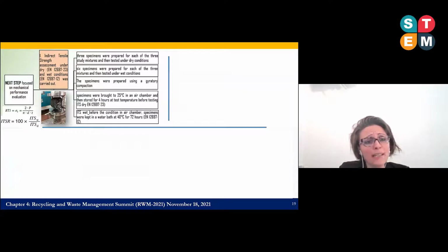The next step focused on mechanical performance evaluation of these mixtures. In particular, we identified the indirect tensile strength. That is the common static test that we carry out on asphalt mixtures, called hot asphalt mixtures, in dry and wet conditions. In particular, we prepared 3 specimens under dry conditions and 6 under wet conditions. The specimens were prepared, as I said before, using gyratory compaction. The test under dry condition was carried out at 25 Celsius degrees after storing the specimens at this temperature for 4 hours in an air chamber.